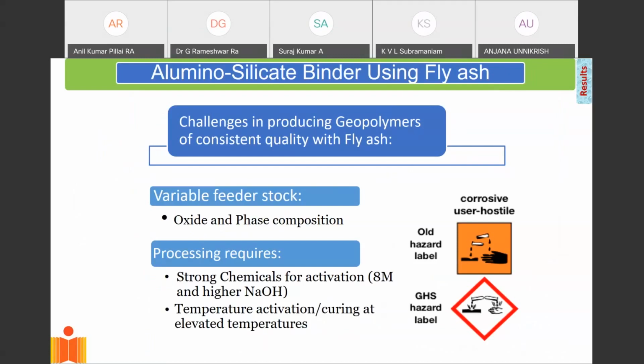Now, one of the big issues here is that currently the production of geopolymers happens in a very alkaline environment. I need 8 molar sodium hydroxide solution and higher. So what people have been using are very, very alkaline solutions, and these are very difficult processing conditions, because very alkaline solutions of sodium hydroxide are very pungent. So basically it's very difficult to use. They're very corrosive, and a little bit of temperature is required for activation. Those are the current challenges.